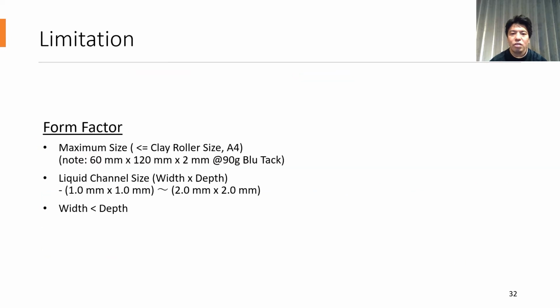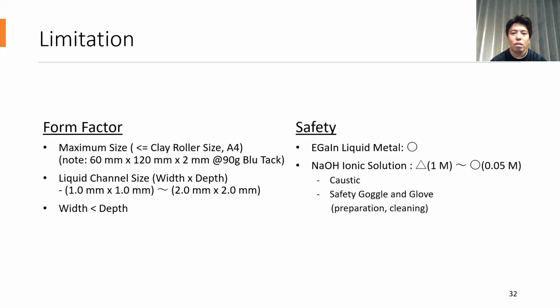As a limitation, maximum fabrication size depends on the clay roller size, which is around A4 paper size. Considering robustness, a 1 mm to 2 mm square liquid channel is recommended with larger depths. Although liquid metal is safe, sodium hydroxide solution is caustic and better to dilute for safety.